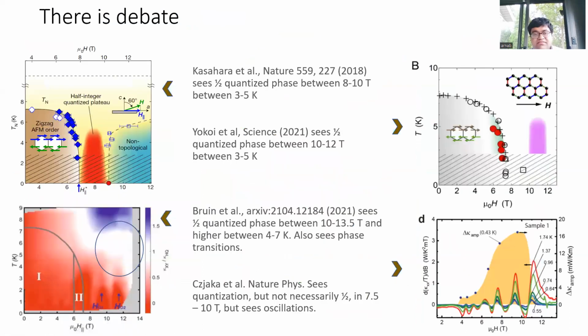Some of these results are somewhat debated in the community, because the Max Planck Institute people saw the same quantized Hall plateau, however at a slightly higher field. It was then repeated by another Japanese group, who saw it between 10 and 12 Tesla, not at 8 Tesla. And the Max Planck group, whose work is now published in Nature Physics, thinks it's actually between 10 and 14 Tesla.